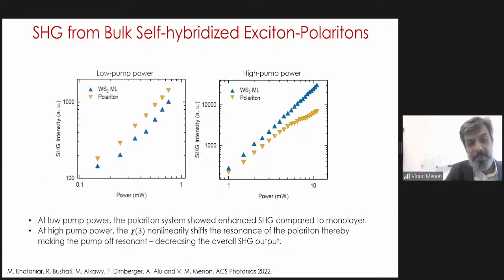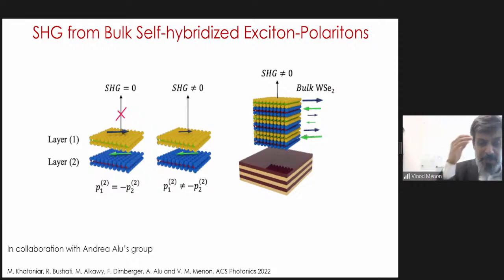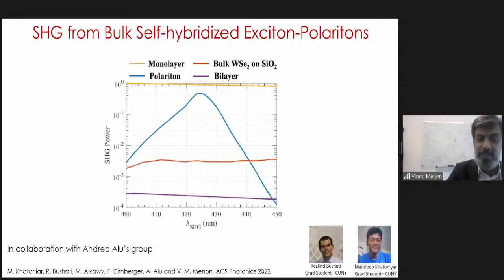Again, this is just the power dependence. So to do this, we collaborated with a group of Andrea Alu, who is a colleague of mine here and at CUNY, and we looked at what is happening to the polarization that you're generating inside the system. So they did their calculation, and then here is what they see. So if you take the bilayer system on its own, it's got a very weak nonlinear response. And then if you take the bulk tungsten diselenide on SiO2, it's like 10 to the minus 2 or something like that, or a few 10 to the minus 3.